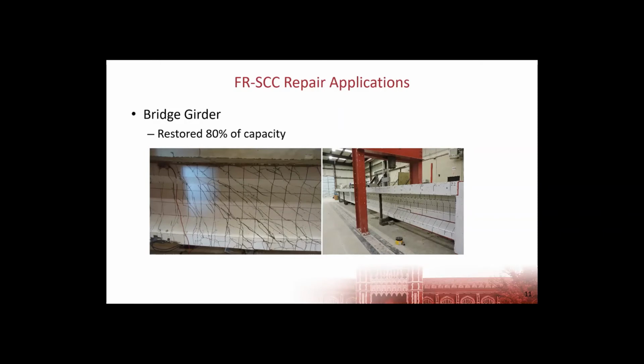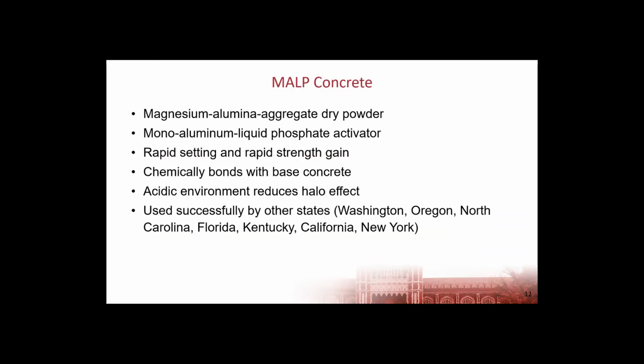That concrete was removed. It was replaced with this fiber reinforced self-consolidating concrete that was cast through holes in the deck to simulate what you would do in the field, and then was retested in the same configuration. And we were able to restore about 80% of the capacity with that fiber reinforced self-consolidating concrete at one end with post-tensioning to restore the pre-stress, and at the other end not post-tensioning, and still able to get around 80% of the original capacity.